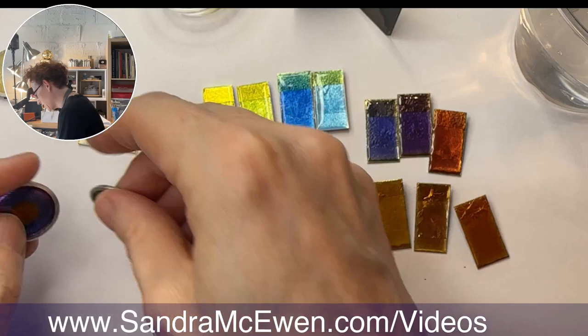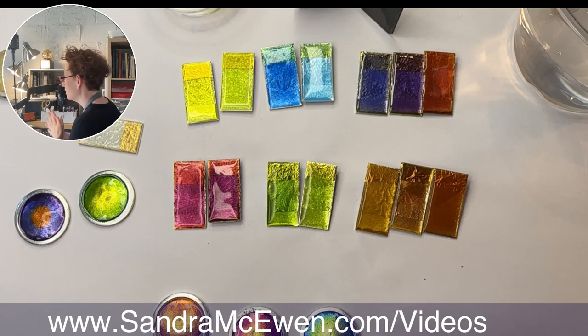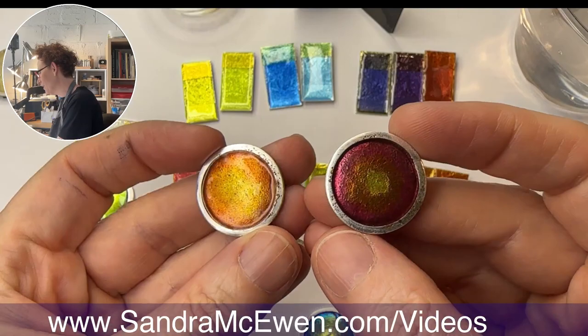I'm looking at the kiln, we're down to 1100. I know I said 1300, but I'm going to set it for 1295, and I'm going to tell you why. My kiln tends to really retain the heat, especially when it's been on all day like it is now. When it hits the temperature again, it keeps going up and up. I don't ever want it to go over say 1320, or else we get cloudiness and milkiness, which we don't want, especially over these dark, glorious colors. Just remember how beautiful these colors are. So I'm going to set it to 1295.